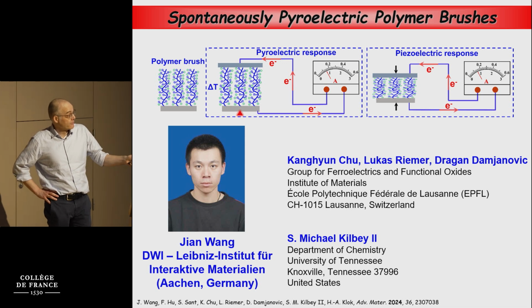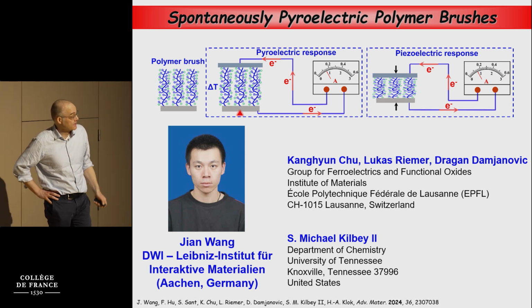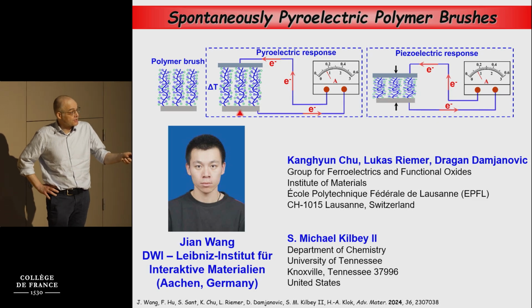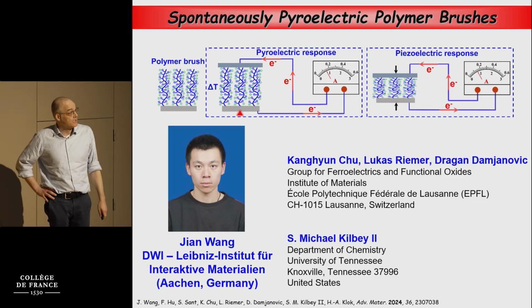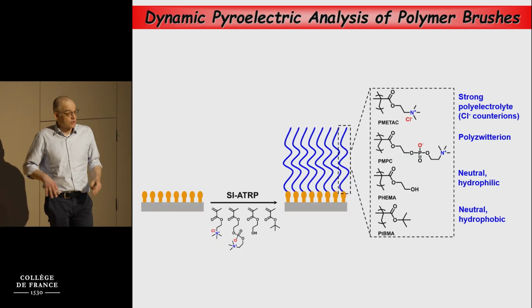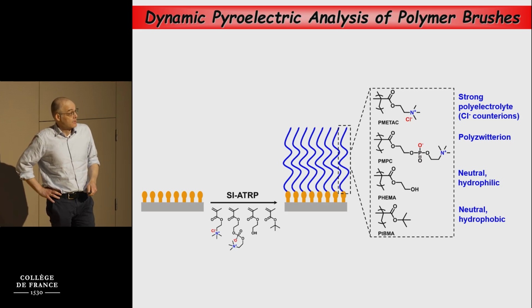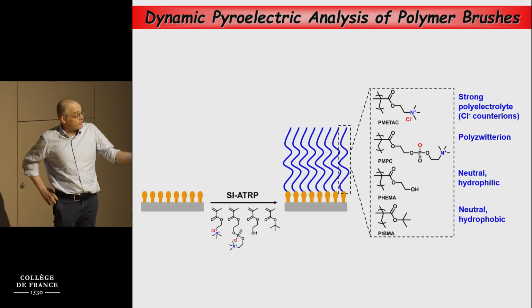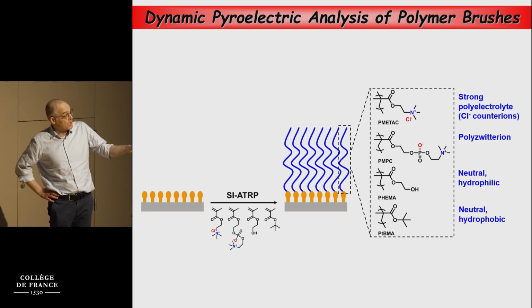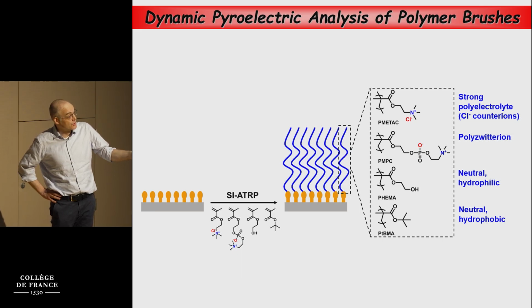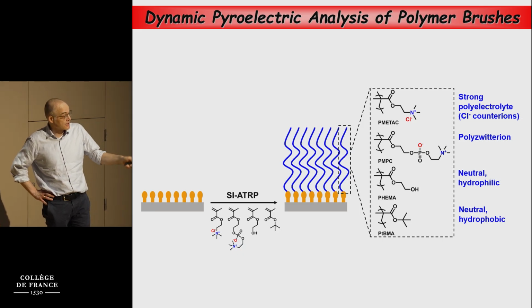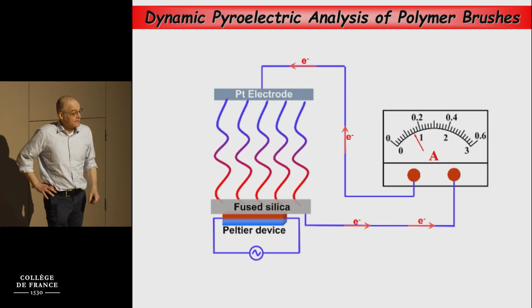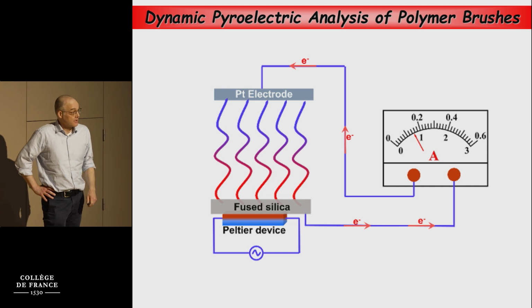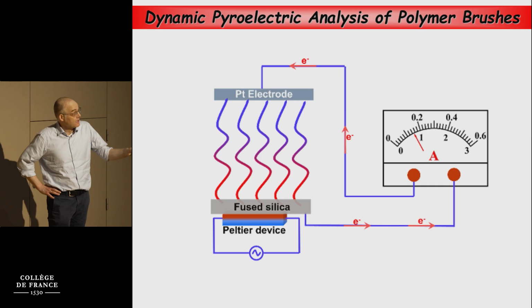The work was done by a former PhD student, Jian Wang, who's now a group leader in Aachen, in collaboration with people at EPFL and at UT in the US. The story is that the student decided to prepare a number of different polymer brushes: strong polyelectrolytes, polyzwitterions, neutral hydrophobic, and neutral hydrophilic polymer brushes. They were grafted from solid silicon substrates. And then, just out of curiosity, he started to investigate their pyroelectric properties in the setup shown here.